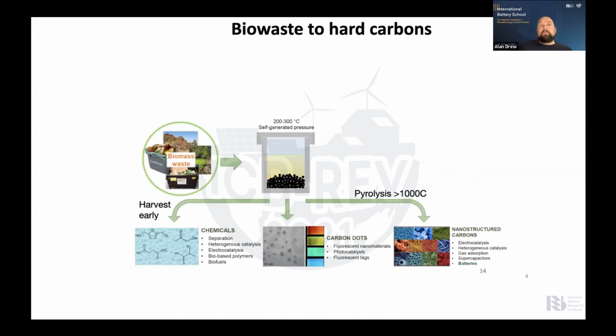Okay, so how do you turn biowaste into carbons? Well, you take a biomass waste product, you put it into a pressure generator at 200 to 300 degrees C, and you cook it for a few hours at that temperature. Okay, if you harvest early, then you end up with chemicals that you can then refine and use for other materials, for other things. So these are bulk chemicals that you can then convert into reagents for other things.